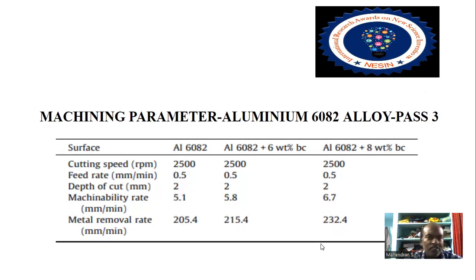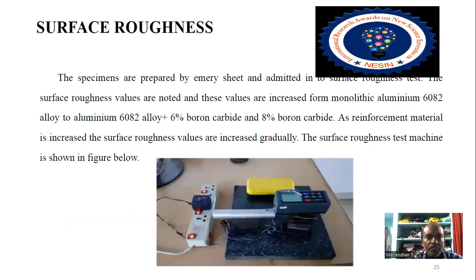This is another set of parameters. Cutting speed is increased to 2500 RPM and the feed rate 0.5 and depth of cut is 2 millimeter. The machinability rate 5.1 to 6.7 millimeter per minute. Metal removal rate is increased 205.4 to 232.4. And these are the various sets of parameters. Automatically machinability rate and metal removal rate are increased.